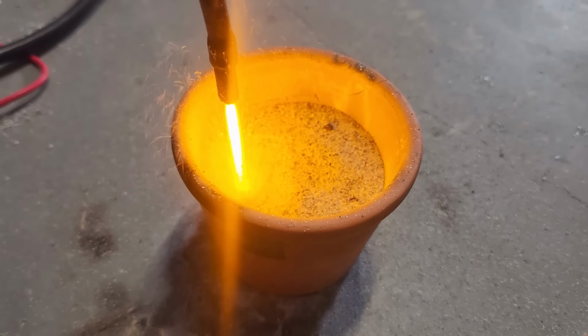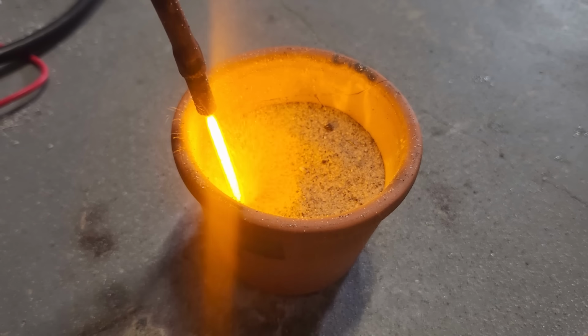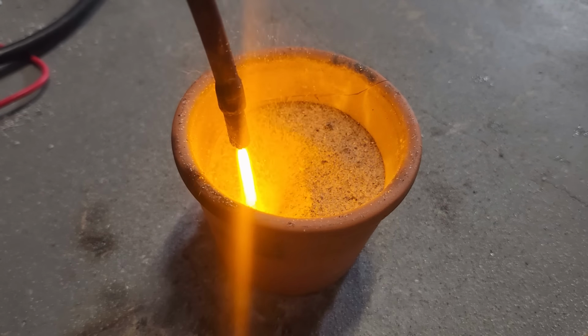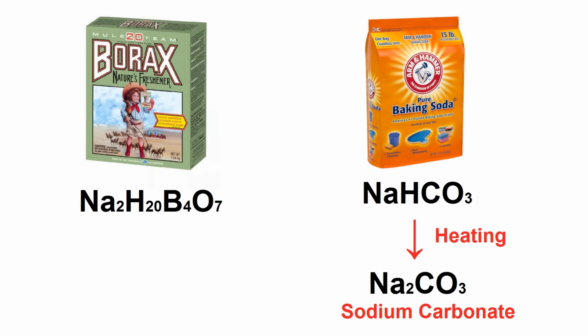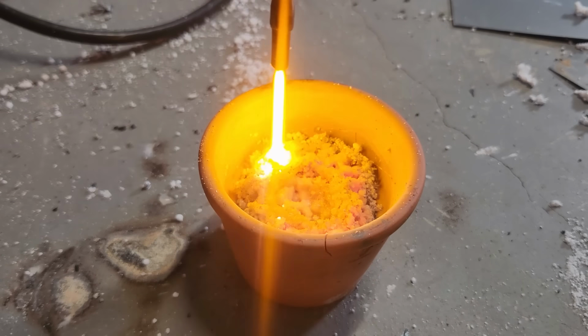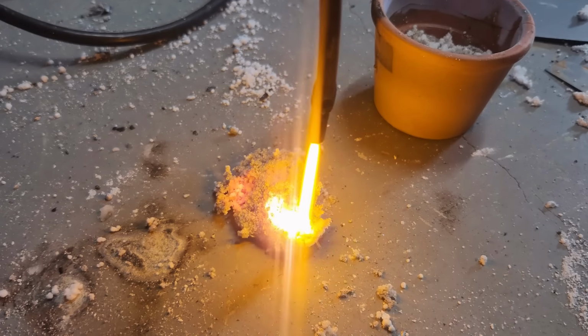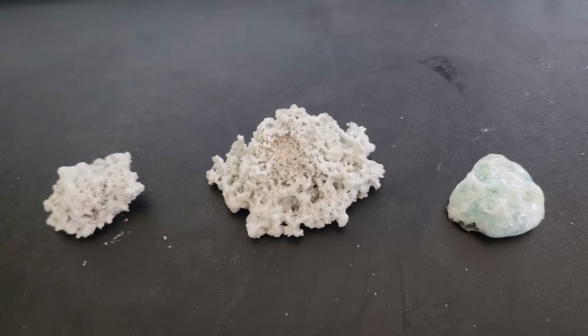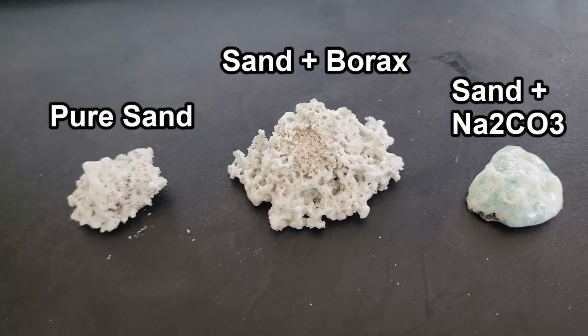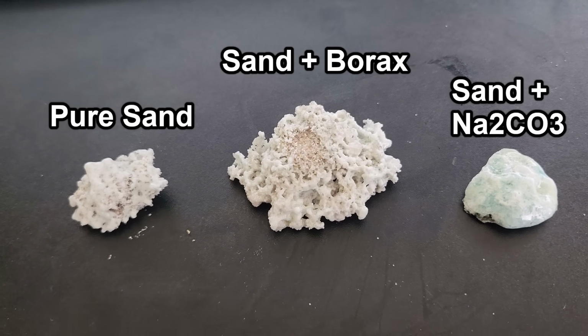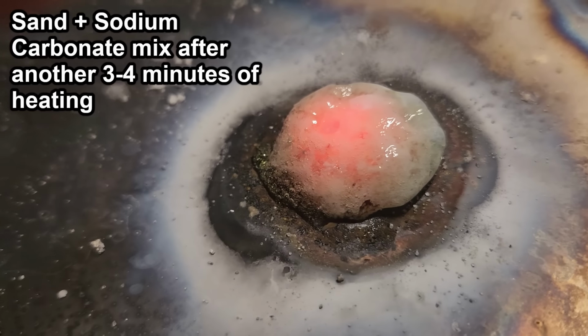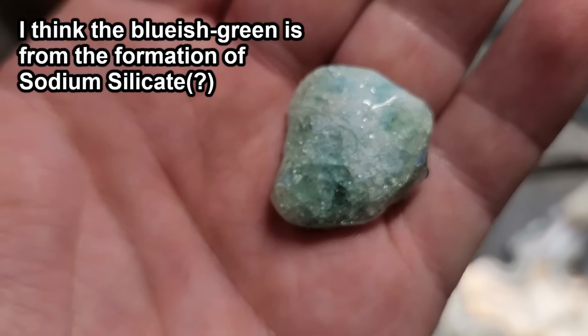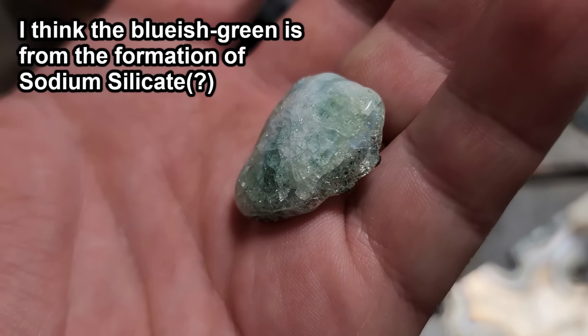It doesn't melt very easily when it's pure, so I tried mixing different salts into it to lower the melting point. The two most common additives are either sodium carbonate or borax. I think between the two of them, borax made it easier to melt the sand, but in both cases the result was really crumbly and brittle, and I never got it to be transparent. With a little more heat, the sand and sodium carbonate mixture actually starts to look like real glass, although it has this funny bluish-green tint to it.